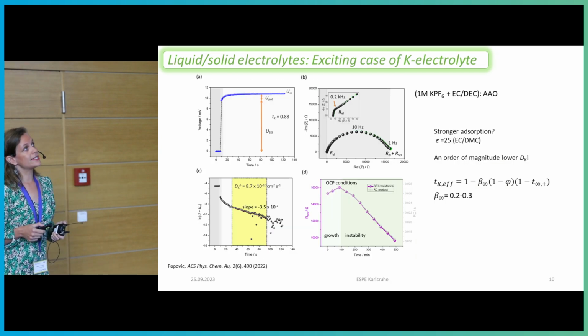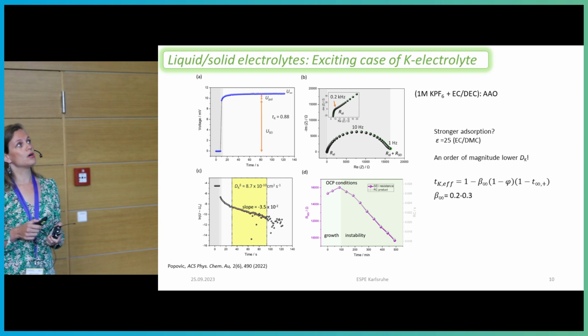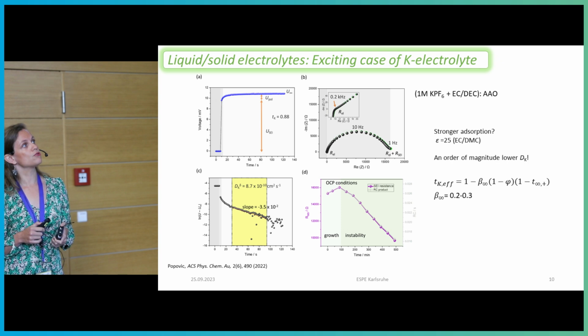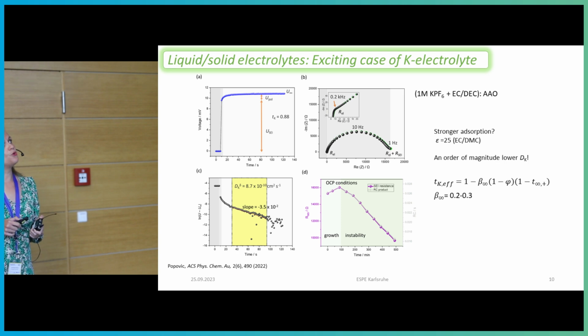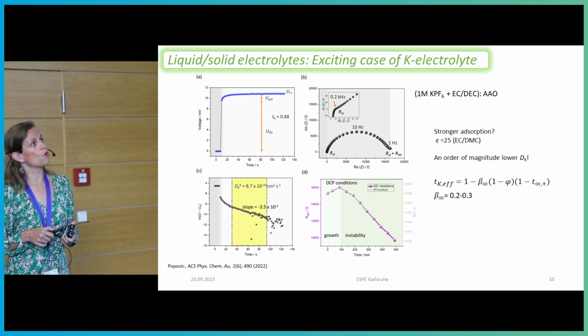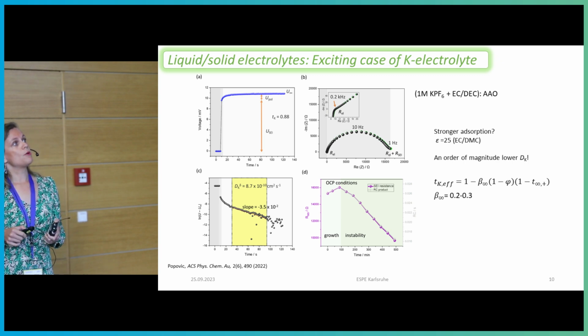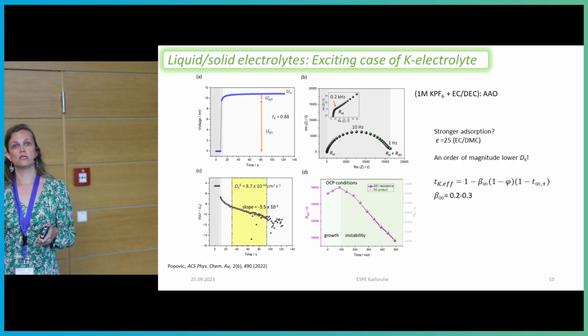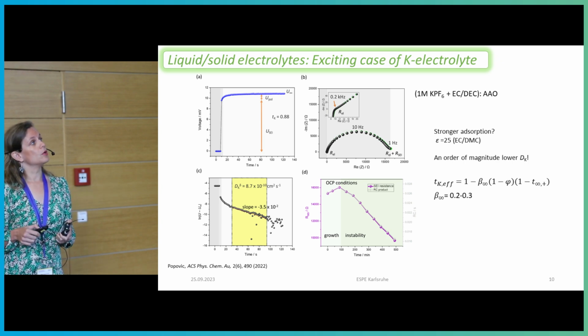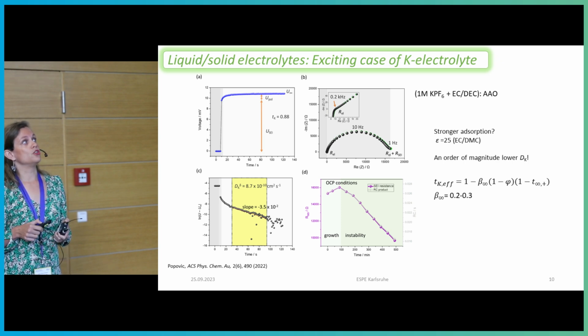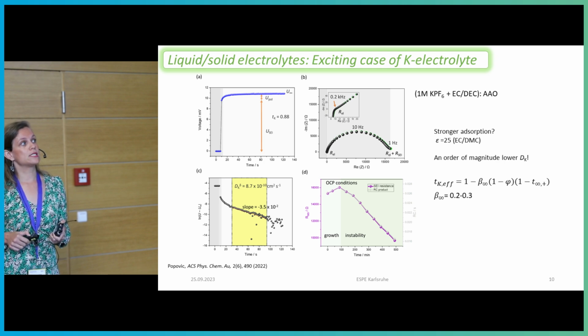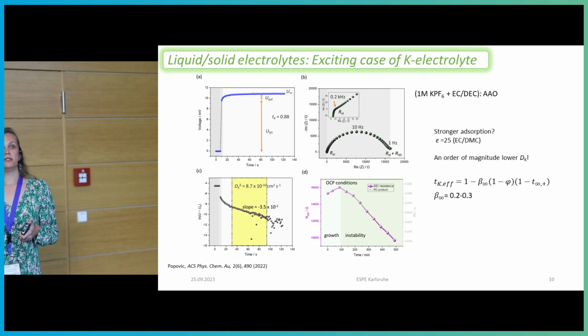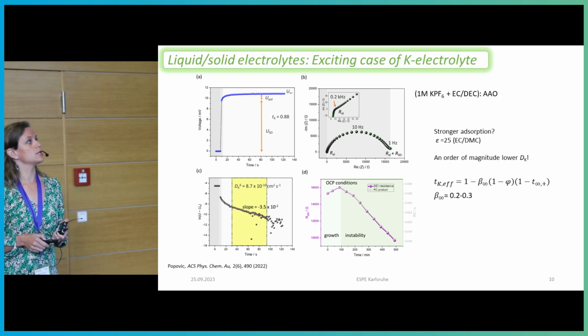And then very recently, an interesting case of what happens in a potassium-based electrolyte in this sense of liquid-solid electrolytes. If we use anodic alumina, and in this case, actually kind of a standard battery electrolyte, which is an EC-DMC with high dielectric constant, we see really, really high transference number with an order of magnitude lower diffusion coefficient, which means in a way that the adsorption is stronger, but the movement of potassium is sluggish. And then the interesting point is also that we could actually measure this transference number, even though we are talking about potassium that does show on the longer run the instability in terms of SEI growth. But initially, it's quite stable SEI, and it's possible to measure the transference number.